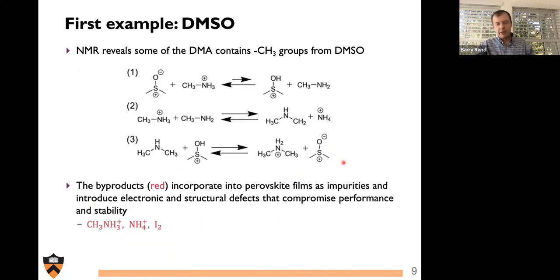And Lin Lu and Jeff Schwartz and Clay Hamill did some pretty careful work a few years back regarding such additional reactions that can occur. And it turns out that indeed within the DMSO methylammonium ink, you can get reactions that form byproducts like not just ammonium, but things like dimethylammonium through this sort of methyl group transfer that leads to, there it is, the dimethylammonium ink byproduct as well.